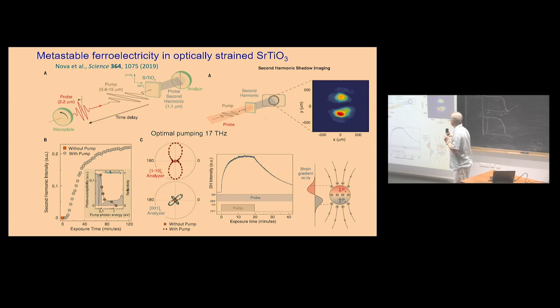My explanation is that when they pumped these higher frequency phonons, they somehow created defects, and they were concentrated in this optical spot, and then these defects create such a strain gradient and charges and so on. It is also supported by their experiment, my idea, that when they illuminated this sample using ultraviolet, then this second harmonic generation disappeared immediately. So ultraviolet, for me, moves the defects out of this spot, and then you don't see the strain gradient any more, and you don't see such second harmonic generation.